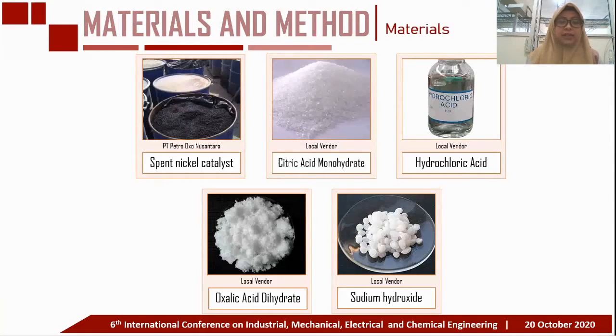Then, about materials, spent nickel catalyst was obtained from PT Petro Oxo Nusantara. The extruded sheet spent nickel catalyst was treated by crushing and sieving through 100 mesh screen. Citric acid and hydrochloric acid were used as leaching agents to separate nickel from other metals. Oxalic acid and sodium hydroxide were used as precipitation agents.